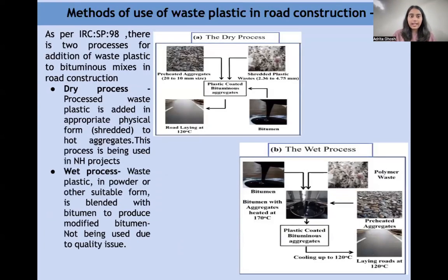Moving to the next slide, methods of use of waste plastic in road constructions. As per IRC:SP 98, there are two processes for addition of waste plastic to bituminous mixes in road constructions. Dry process: waste plastic is added in appropriate physical form to hot aggregates. This process is being used in NH projects.